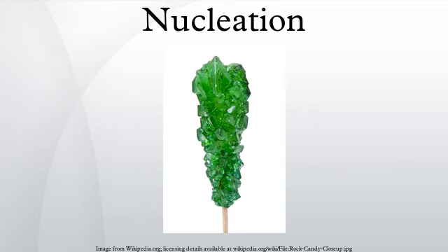modern computers are powerful enough to calculate essentially exact nucleation rates for simple models. These have been compared with a classical theory, for example for the case of nucleation of the crystal phase in the model of hard spheres. This is a model of perfectly hard spheres in thermal motion, and is a simple model of some colloids. For the crystallization of hard spheres, the classical theory is a very reasonable approximate theory. So for the simple models we can study CNT works quite well, but we do not know if it works equally well for say complex molecules crystallizing out of solution.